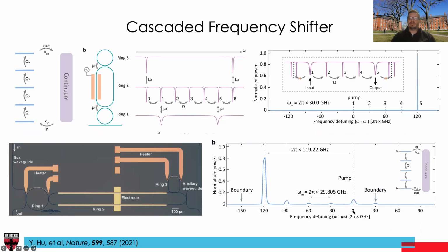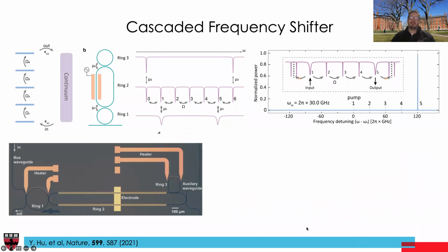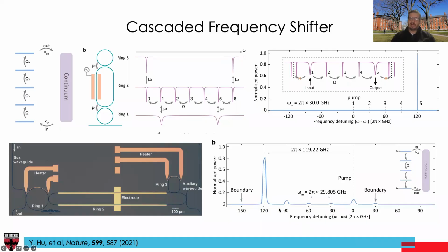We were able to shift here with maybe 80% efficiency, not 99% efficiency. We were able to put light at this resonance, and then applying a 30 gigahertz drive, we could shift the signal by 120 gigahertz. By reducing the losses, improving coupling and whatnot, we could eliminate these intermediate steps. So it's kind of cute to see these intermediate steps as well in the process, and get most of the light, actually 90% plus light, exiting at this frequency.